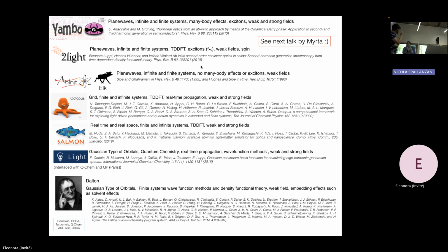Again, to complete the ionic contribution, you need to displace the atoms. For what Lisa did, I think she wrote a Taylor expansion where she takes into account the change of the displacement of the atom, the coordinate of the atom. So these enter in the susceptibility, which you consider the ionic susceptibility plus the electronic susceptibility.